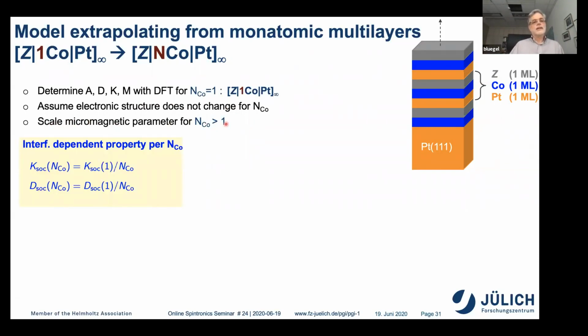So we know that the spin-orbit contribution to the magnetic anisotropy and the Dzyaloshinskii-Moriya interaction is certainly an interface-related quantity. Therefore, relative to the number of cobalt layers, you have to divide these quantities per number of cobalt layers if you want to have your energy per cobalt layer. Very differently behave the shape anisotropy and, for example, the spin stiffness. These are bulk quantities. So per cobalt layer, they are always the same.